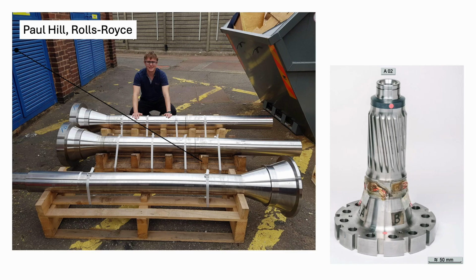Here you see Paul Hill from Rolls-Royce sitting in front of 3 blanks of the new shaft alloy. And of course it has to have machinability, and it does have that machinability because there are some intricate features that would be machined onto the shaft. So this is another example where density of steel actually beats nickel alloys and is present in a civil engine which actually flies. So the case that I'm making is that density is not a really bad characteristic of steel.